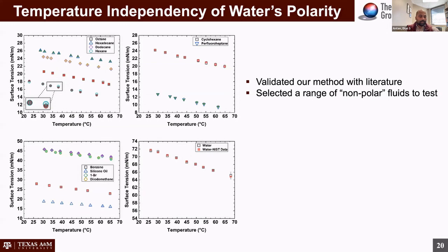So we first validated our method, our measurements, with the literature. Literature is shown in the shaded symbols, and our measurements are in the open or unshaded symbols. We have fairly good agreement between our measurements and the literature for a wide range of fluids. We picked some truly nonpolar fluids like linear alkanes and the cycloalkane and a perfluorocarbon. We have water, which is a fairly polar fluid, or the most polar fluid in the chemistry literature. And we have some fluids that are slightly in between.